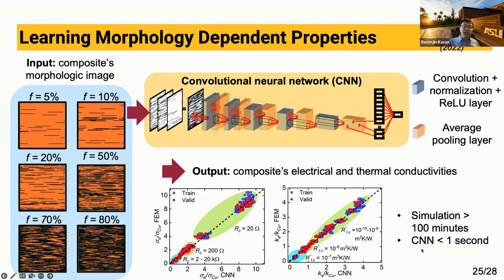But with the trained convolutional neural network, it takes less than 1 second to predict for one image. So even though you change the distribution of CNTs, if you change the size of the domain, still our model can predict for those images within less than a second. So I thought that those were pretty interesting demonstrations of using deep learning for some fundamental thermofluidic problems.